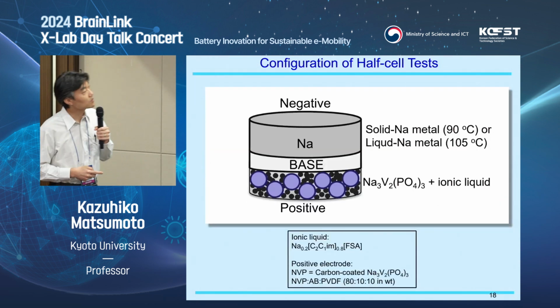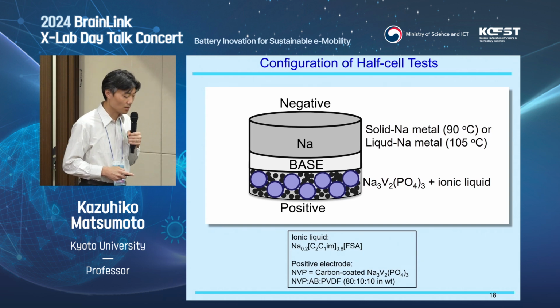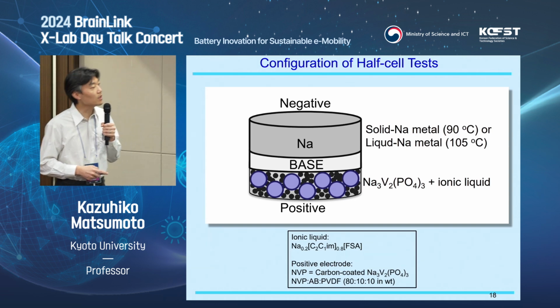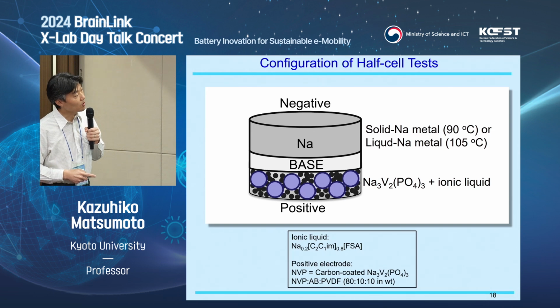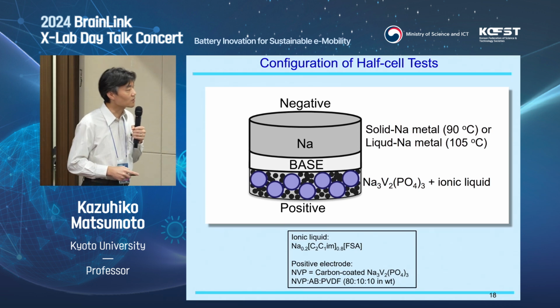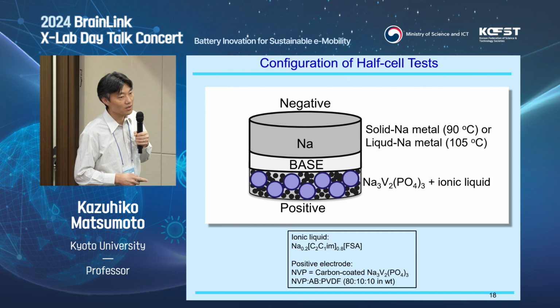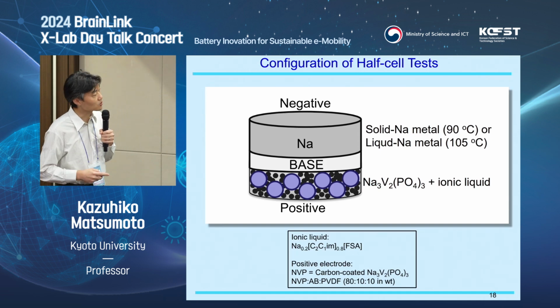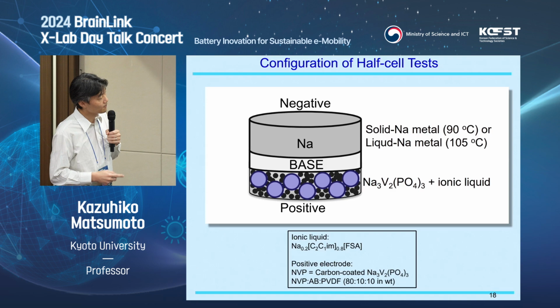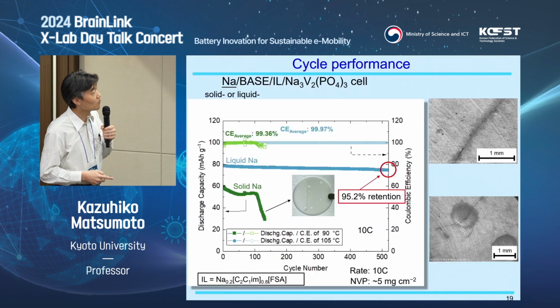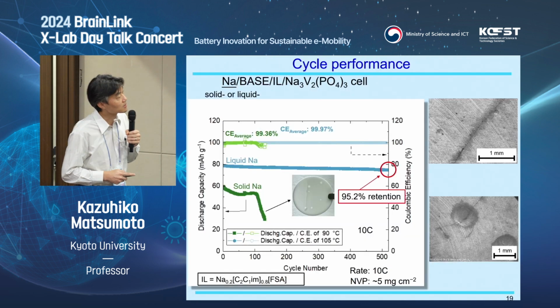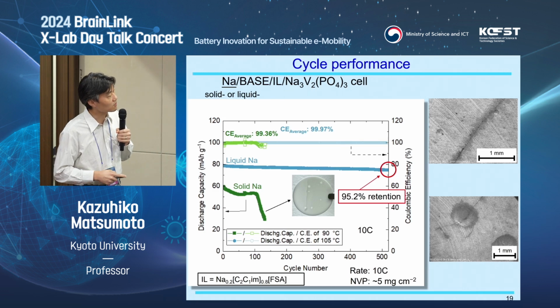And then we moved to that half cell test with solid sodium and liquid sodium metal combined with again NASICON type Na3V2(PO4)3 positive electrode. But here the beta alumina is solid, and then this NASICON type is of course solid. So solid-solid contact is not very good. So again, we added ionic liquid a little bit as an interface and solid ion conductor. Then we compare the two different cases, the cycle performance over like 500 cycles.